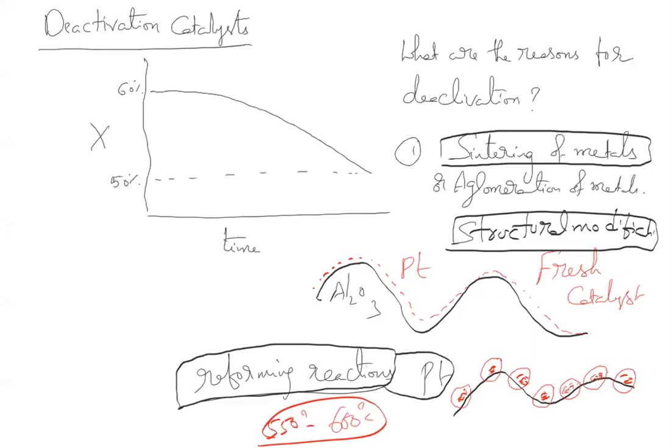How do you regenerate the catalyst? You pass some chemical medium, basically chlorine, so that the chlorine disperses the catalyst once again back into the system. In the olden days, reformers had fixed bed reactors where one was the reactor and one was the regenerator. Nowadays the technology is so advanced that the catalyst on its own moves from the reactor to the regenerator, so it is a cyclic operation. One reason for catalyst deactivation is sintering of the metals.